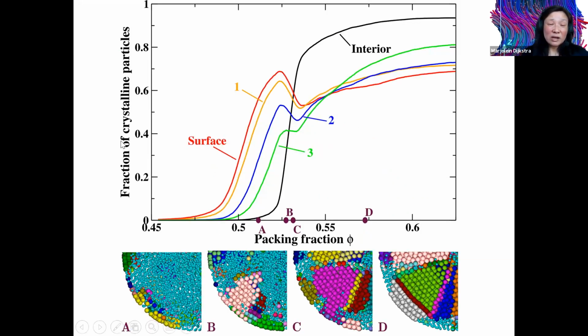So here we calculated, for instance, the fraction of crystalline particles in the surface layer, and then the first layer, the second layer, and the third layer. This is as a function of packing fraction, but because we compress the system slowly, because the solvent evaporates out of these emulsion droplets, the packing fraction can also be seen as time. So the surface starts to crystallize, then the first layer, then the second layer, then the third layer. Then the interior starts to crystallize. If the interior starts to crystallize, the outer layers melt again. But then if this HCP plane is grown on top of these tetrahedral domains, then the outer layers crystallize again.